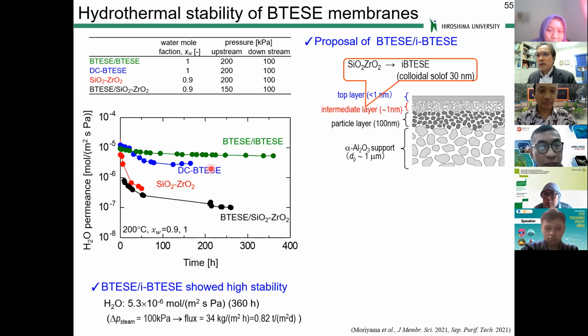Okay. In this case actually we have not examined in detail, but we believe the silica zirconia is an intermediate layer which has a pore size of 1 to 2 nanometers. And then this membrane is coated on the silica zirconia. What I guess is that the silica zirconia layer is not as stable as iBTESE. iBTESE is hydrophobic. Okay, so silica zirconia is a hybrid of silica and zirconia. Zirconia should be stable at high temperature and even under hydrothermal conditions, but the silica is not so stable. So this silica is somewhat decomposed, dissolved in the water phase, and then migrates to some small regions, and then makes some dense layers.